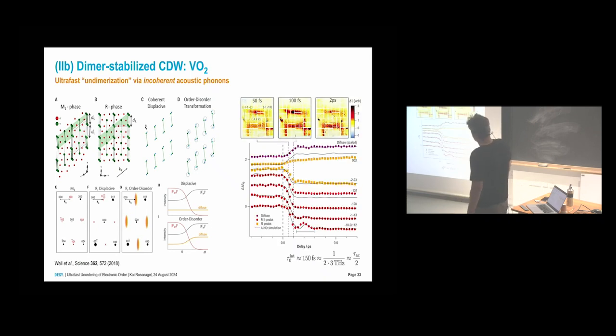And they see in the experiment extended areas of diffuse intensity occurring at a very fast time scale. This here is the relevant intensity transient of the Bragg peaks, and here you see the occurrence of the diffuse intensity happening on a very fast time scale, which corresponds to about half an oscillation period of the relevant phonon mode, which in this case is this 3 terahertz mode.